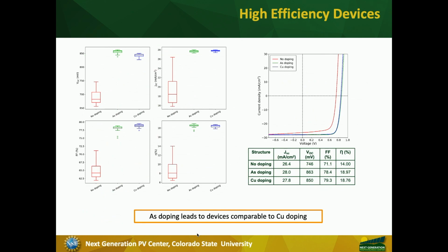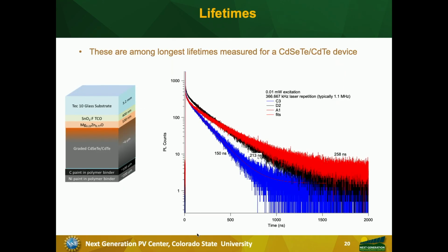Now, here are comparisons of 3 different devices. This is no copper or no arsenic. Here is a copper and arsenic. And these are all 18.9, 19% devices that we have made on the system. And these are also some of the highest lifetimes that we have measured among the CSU cadmium telluride devices: 258 nanoseconds, 213. If you didn't have all the passivations and the selenium and the other treatments, you couldn't get these kinds of numbers. It would be in the less than 10 nanosecond kind of range.